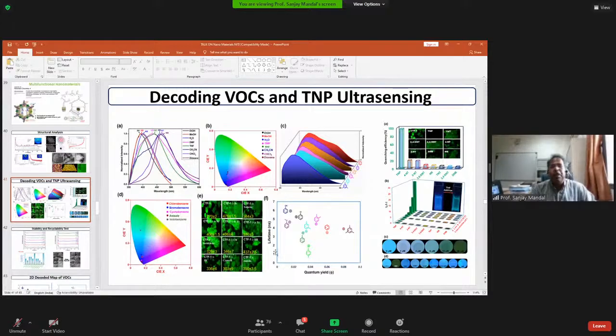And we could do a plot of lifetime versus quantum yield to show you that you tell me orthoxylene, metaxylene, or paraxylene, I can tell you where they are coming from. And by fluorescence microscopy also, we could look at their changes. On the other hand, when you look at the TNP, you can see it is very selective, and through fluorescence microscopy, we can see that the green color is gone. And visually, you can also see what is happening with this, right?